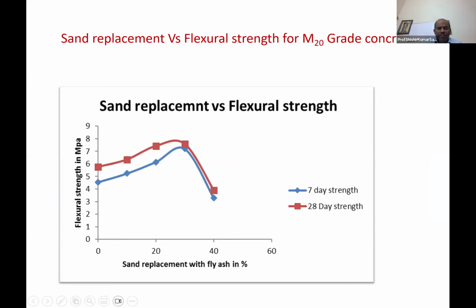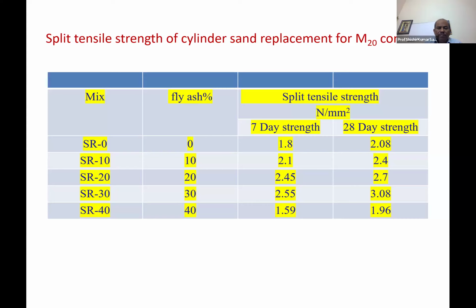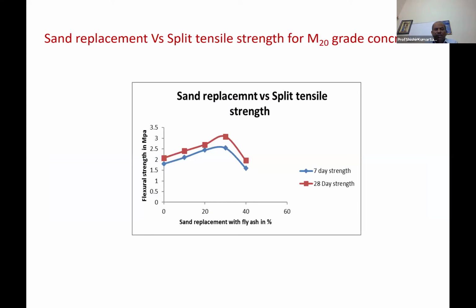Then we have results on the split tensile strength. In a similar manner, 30% seems to be the optimum percentage. Same thing, we can get it from the graph as well. At least 30% sand can be replaced conveniently. It depends whether your structure is subjected to compressive forces or tensile forces. Accordingly, you can consider the corresponding strength and find out the optimum percentage.